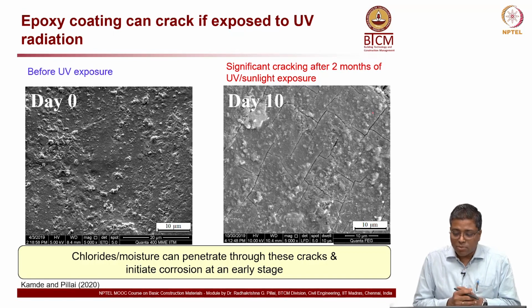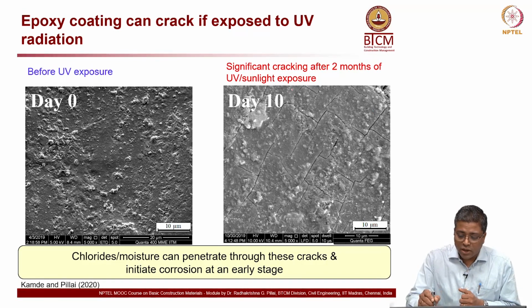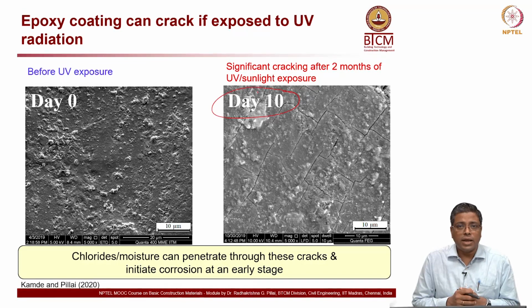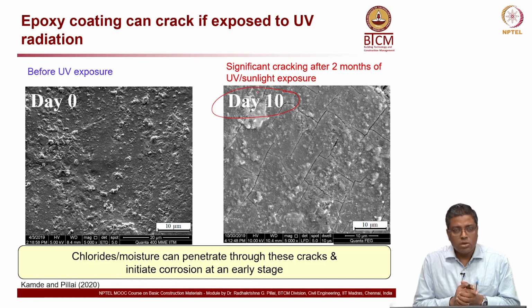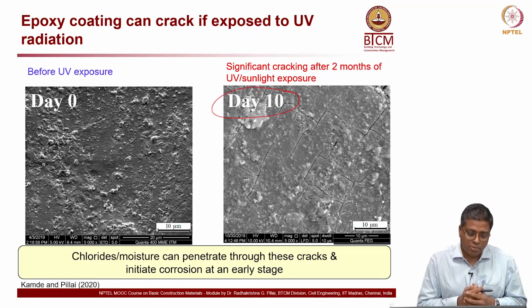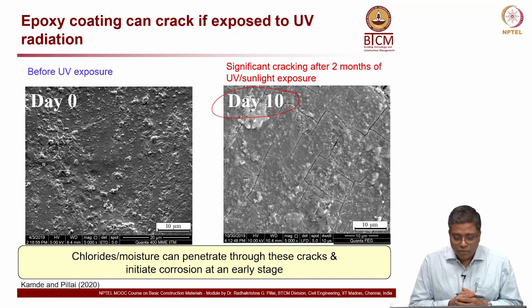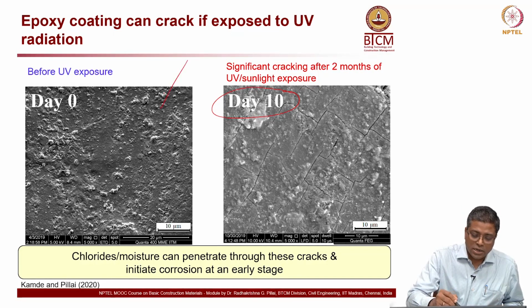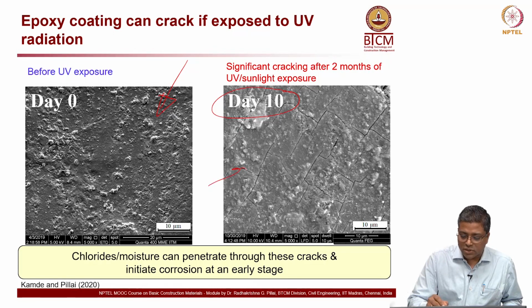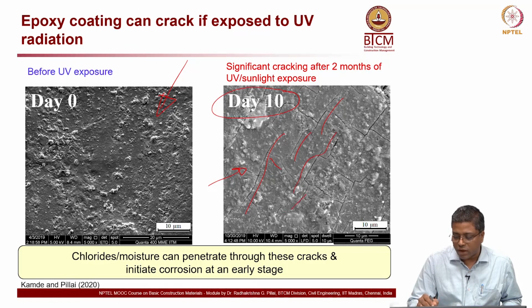So, in some lab experiments we saw that in very few days, even if you expose it to sunlight, within a month you will have a lot of cracking on the epoxy. This is also a microscopic image, or micrograph, which shows that initially there is no cracking, and then after some time you will have a lot of cracks.